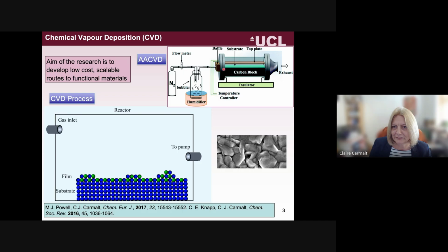In the reactor, you have a carbon block that heats up your substrate. So that would be our glass substrate. And it depends what temperature relates to which film that you're trying to deposit. So it could be anything from 150 degrees up to 550, although the industrial process takes place at higher temperature, but that's above the softening point of glass. So we tend to stay below that at about 550. We have a top plate present, and that just allows the aerosol to have laminar flow through the reactor. And of course, once your aerosols come into this heated area, then the solvent evaporates away and your precursors are then ready to decompose on the heated substrate and hopefully grow your thin film.